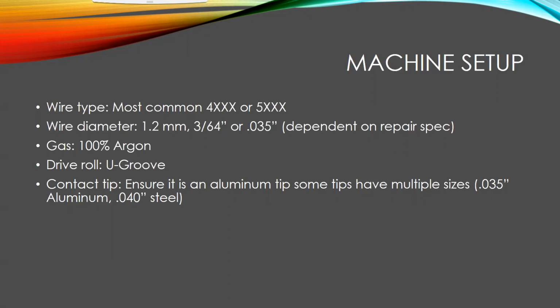Wire diameters: 1.2 millimeter, 3/64, 035. It's all dependent on the repair spec, really, and what the auto manufacturer is calling out that they require for that repair. So I'd highly recommend for your setup for MIG aluminum that you check with that manufacturer first. Shielding gas: whenever you're welding aluminum, typically you'll use 100% argon. And then drive rolls, this is critical. The type of groove is a U-groove. What that does is it allows that wire not to be crushed, because if you have a V-groove, it's going to put a pinch on that wire and it's going to misshape the wire, and then you might see some arc performance issues.